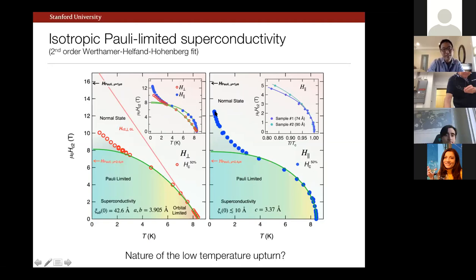One of the things that I don't think there's consensus on, by the way, among my collaborators here, but at least that I keep getting excited about, is that if I extrapolate to the low temperature limit, this upturn looks like it's going to hit in the vicinity of the bare Pauli scale. Namely, if you forget about the susceptibility enhancement, and just go to a free electron value, that seems to be not far from where we might be headed at low temperature.